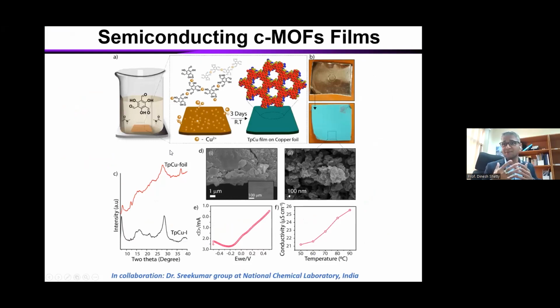Then we thought of using them as a salt-free system, which means, for example, we use copper salt and TP. Instead of that, how about dipping a copper foil, for example, inside the TP solution? Can it form a MOF? So we could easily see a beautifully formed MOF on the surface of the copper foil, and we characterized it, and it is showing semiconducting nature, and we ended up getting the semiconducting conjugated MOF.